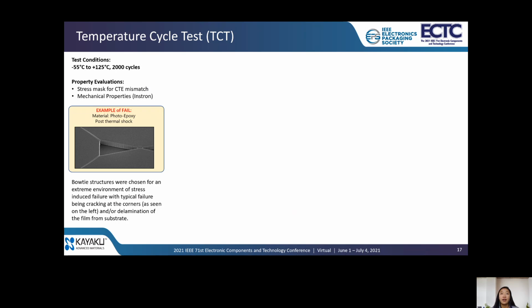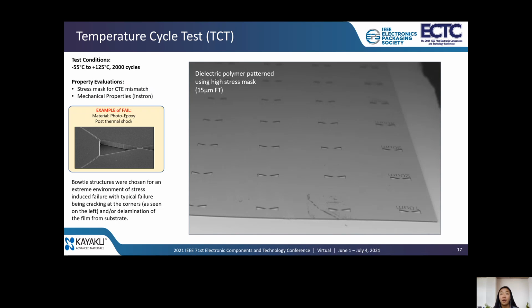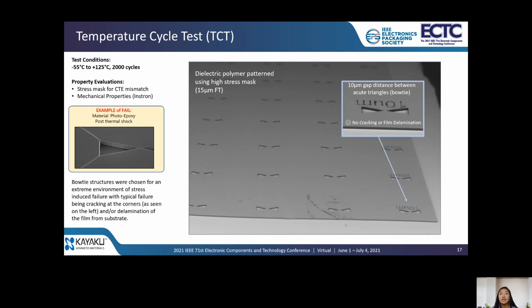So a 15 micron thick film was photo patterned using an in-house stress mask on silicon wafers to create this bow tie structure with gap distances ranging from 10 micron all the way up to 300 micron. You can see some of those examples here. Temperature cycling testing was completed ranging from negative 55 degrees C to positive 125 degrees C for 2,000 cycles. And PRL-29 successfully passed all 2,000 cycles. No cracking or delamination of the film was observed.